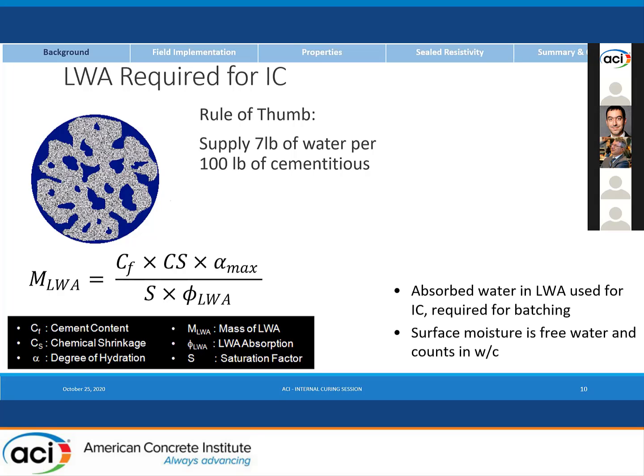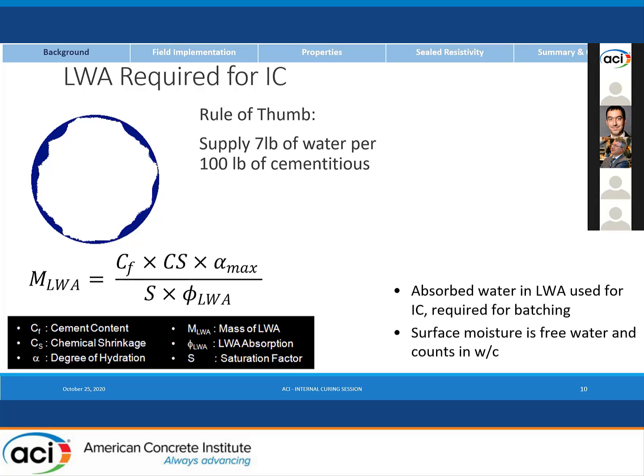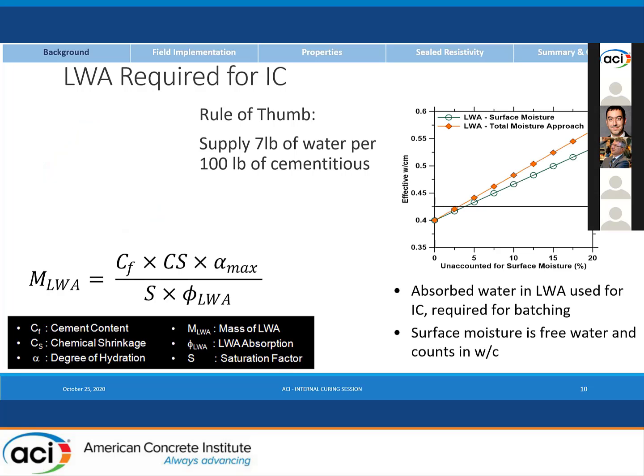We have something with surface moisture and then absorbed moisture. So we need to know what the SSD condition is so that we can determine how much internal cured water we are actually providing. And then we need to know what's on the surface, and that's primarily a critical item because if we don't account for the surface moisture on the lightweight aggregates, just not accounting for a very small percentage of that potential moisture, we quickly can exceed, say, a target specified water to cement ratio.